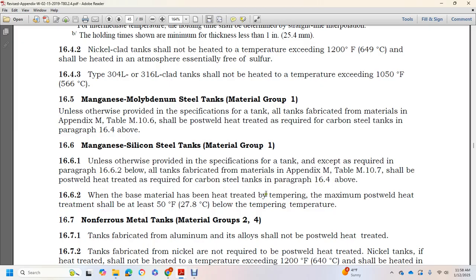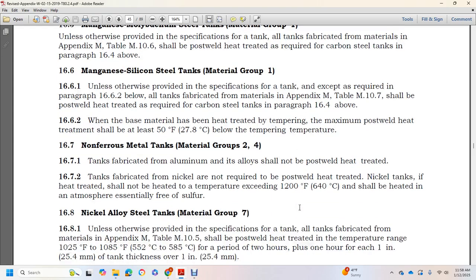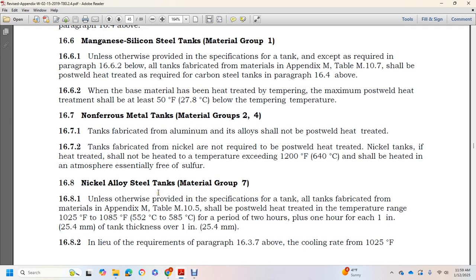When the base material has been heat treated by tempering, the maximum post-weld heat treatment temperature shall be at least 50 degrees below the tempering temperature. Non-ferrous metal tanks, material groups 2 and 4: tanks fabricated from aluminum alloys shall not be post-weld heat treated. Tanks fabricated with nickel that require post-weld heat treatment and are heated to a temperature exceeding 1200 degrees Fahrenheit shall be heated in an atmosphere essentially free of sulfur.